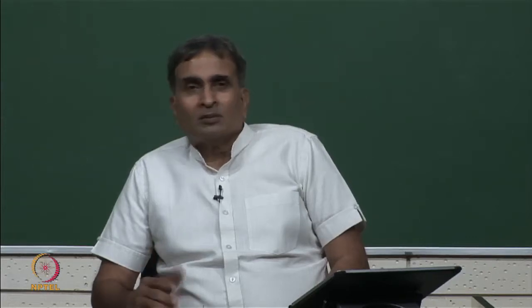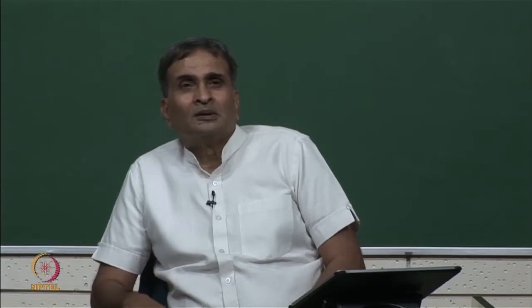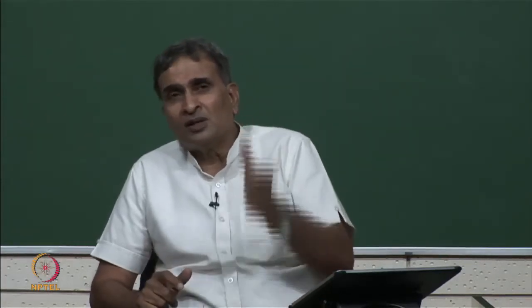In the winding zone, a small amount of underfeeding is applied to produce tight packages. If heat stabilization has been done, spin finish oil may need to be replenished, since the spin finish used on POY — which is also used for false twist texturing — may have components that evaporate during heating. Replenishing at the winding stage compensates for this, though it is not highly critical unless the finish quality is poor.